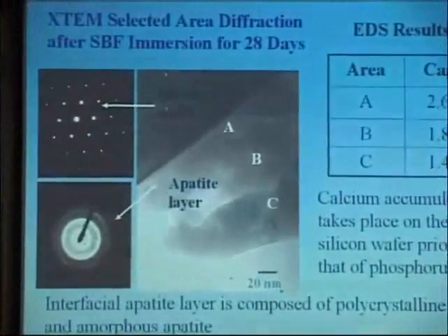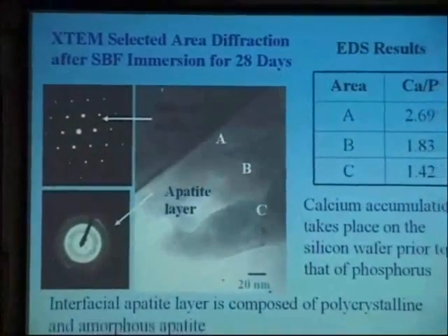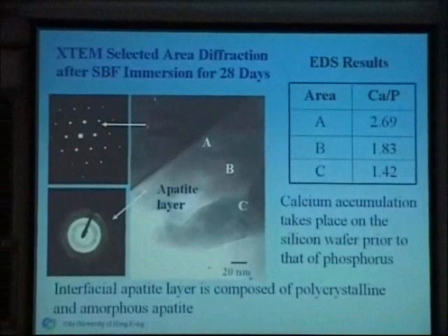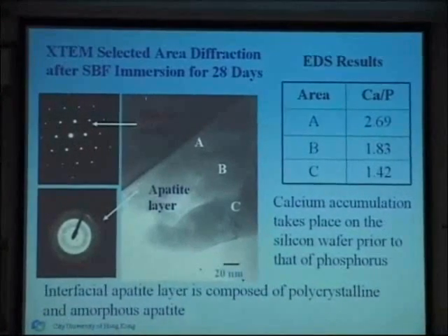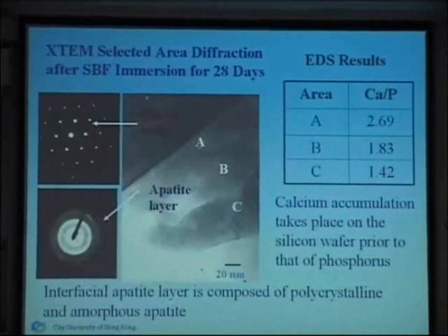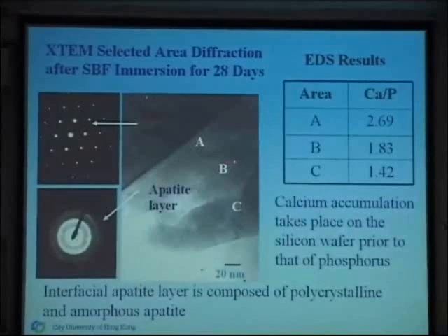This is a cross-section. The silicon wafer, we do have this layer. So we did some X-ray diffraction. We found a single crystal silicon, which is fine. We have an amorphous layer here. And then here we did some EDAX, X-ray analysis looking at the elemental composition. Region A has more calcium than phosphorus. Region B, less. And C is almost 3 to 2, which is the natural composition, Ca3(PO4)2, right, chemistry. So 3 to 2. So this is about right.